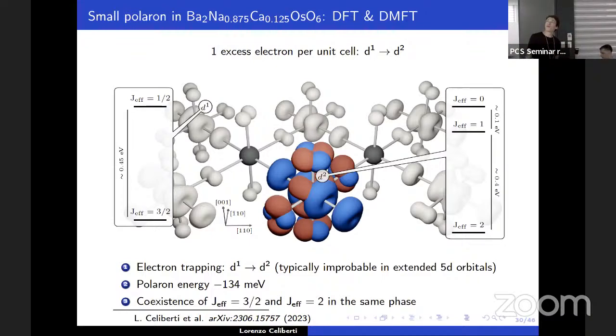We also performed the DMFT calculation here to show the multiplet structure of these sites. Basically you see that at the polaronic site you have a J effective 2 state, whereas at all other sites the J effective 3/2 structure is preserved. So you have a phase where these two different spin-orbital structures coexist together.